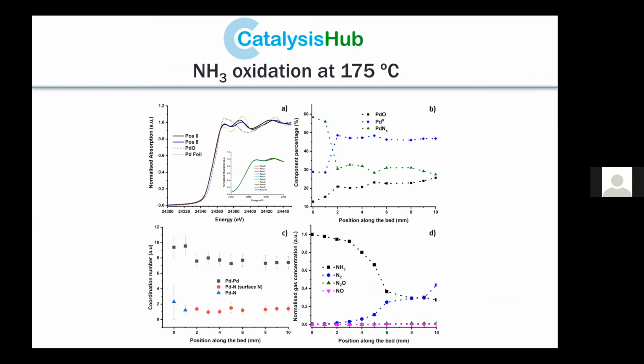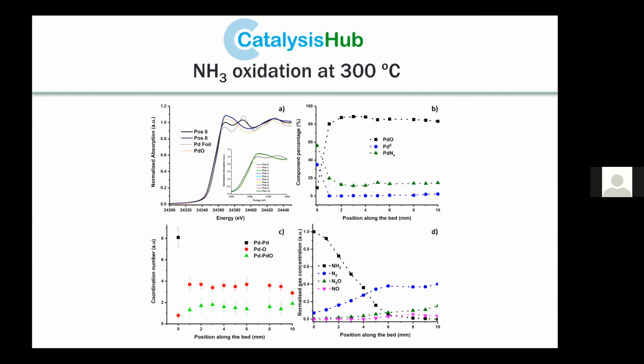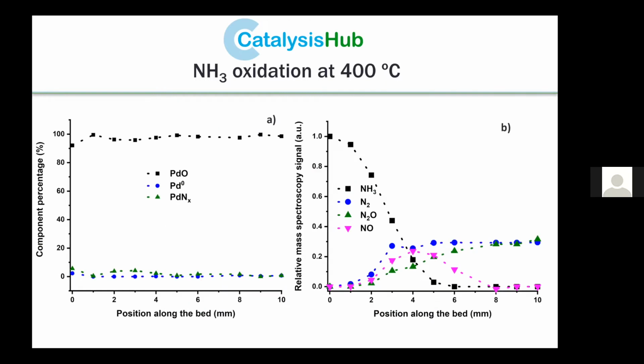In fact, as we increase the temperature to 300 degrees, higher oxidation products appear, until at the inlet, the system is still predominantly palladium nitride. However, as we move forward, the palladium nitride concentration drops dramatically, and therefore we start to see a higher amount of NOx being produced. So it is clear that there is a correlation between the amount of palladium nitride and the amount of nitrogen produced and the selectivity toward nitrogen, which is further exemplified when we increase the temperature to 400 degrees.